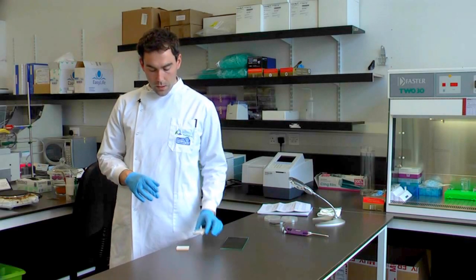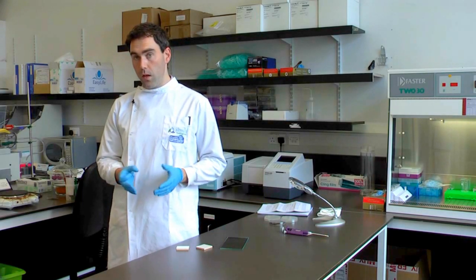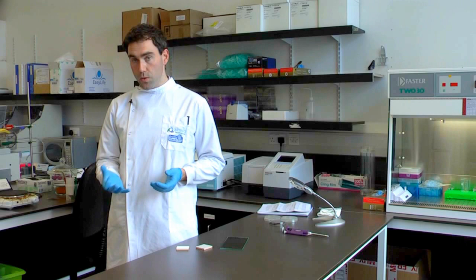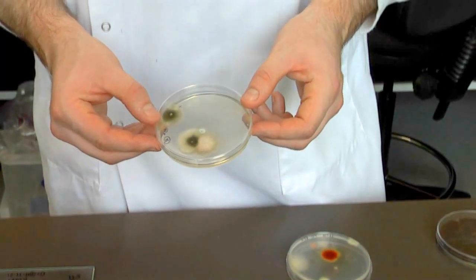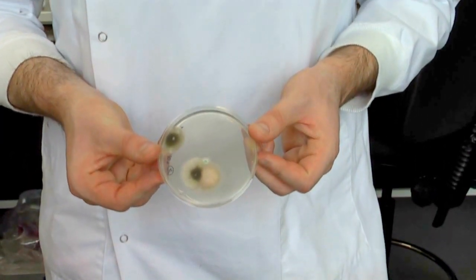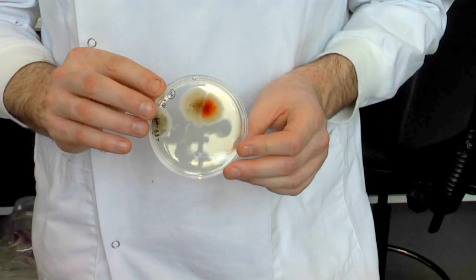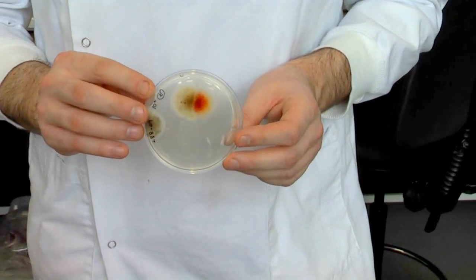After a period of light exposure, the number of viable bacteria that are left on the surface of the treated material is quantified by initially washing and then plating out on a suitable agar. How this is standardized then is against the recovery of bacteria at time zero and then the recovery of bacteria against the untreated surface.